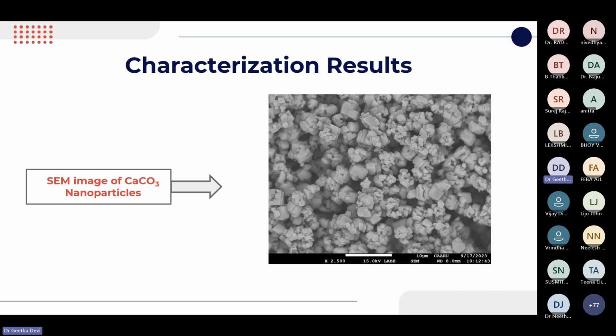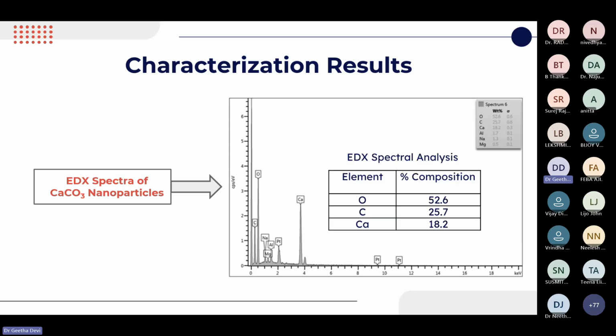This is the scanning electron image of the calcium carbonate nanoparticles, at a magnification of 2500. We can see that the particles are well formed, and it is high yield, which shows the nanoparticles are synthesized. Also, the purity of the nanoparticles was assessed using energy dispersive X-ray analysis.